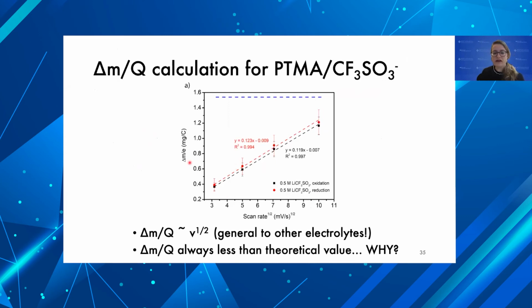However, we found that our delta M over Q, that's the mass exchange per electron, was lower than the theoretical value that we anticipated, if we assume it's just a triflate. And so that means something else is transporting. And as I hinted to you, it's the lithium cation that is also transporting. So that's kind of changing the apparent mass exchanged. We also found that this scales with scan rate to the 1/2. I don't have time to get into it, but it is because it is an electron diffusion limited process.